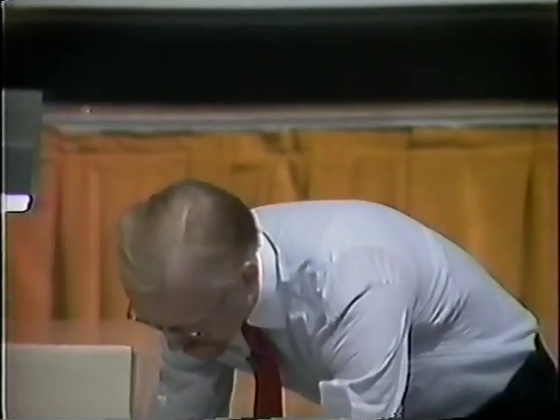Nate Hoffman, E-Tech, Rockwell. Question with respect to an actual microstructure. When you put the deuterium into the palladium, you get regions that are highly distorted surrounding regions that aren't very distorted. And that same Fuller paper, which I think is back there, shows very nice metallography of these regions that are highly distorted and within regions that aren't distorted at all. Does your theory take into account this sort of behavior within a single grain? If I can find it here, then